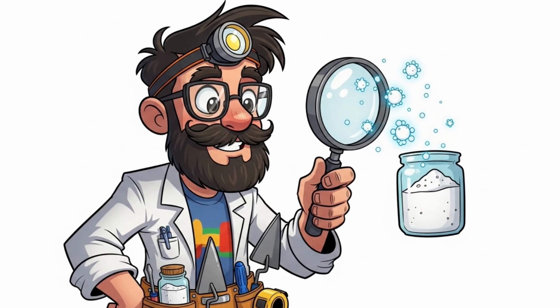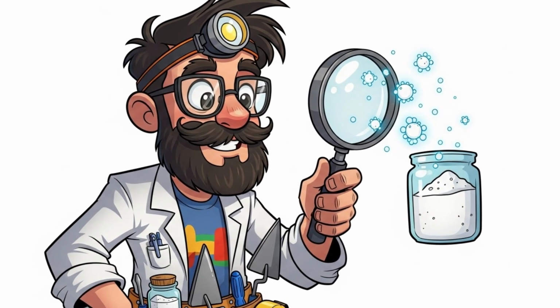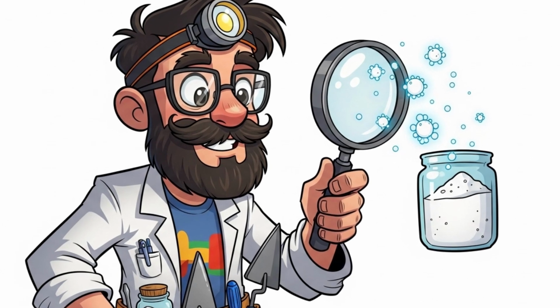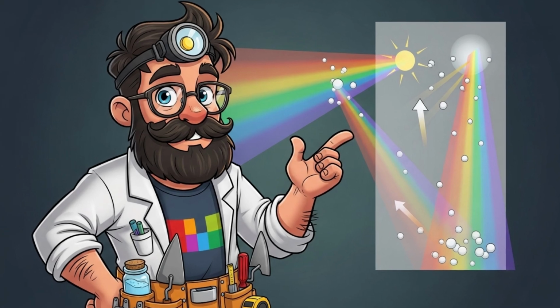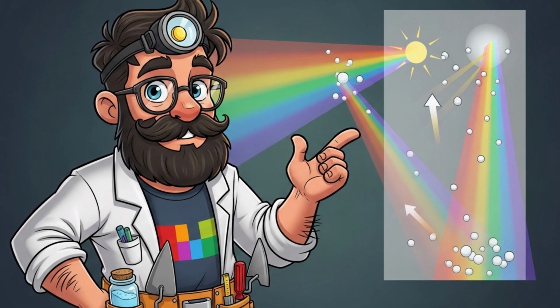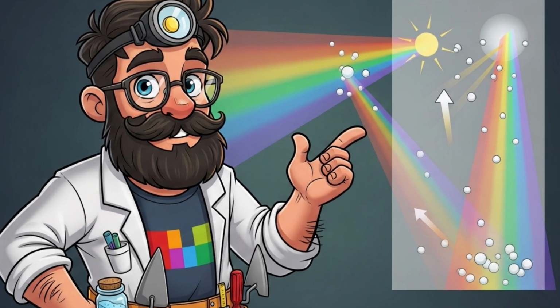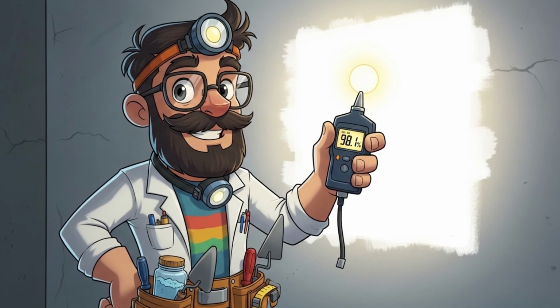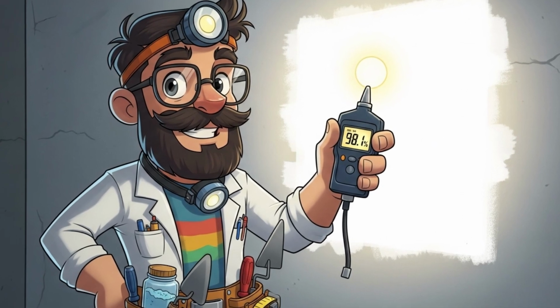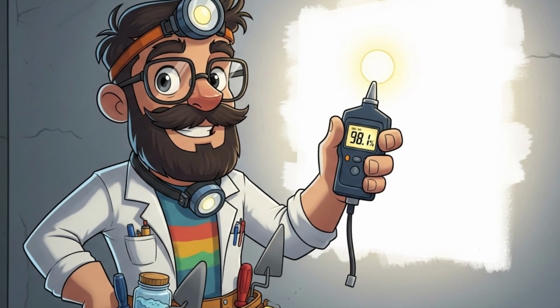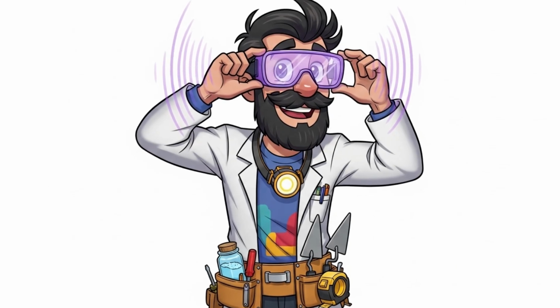Their paint uses barium sulfate nanoparticles at a 60% concentration in a carefully calibrated range of particle sizes. Each particle size scatters a different wavelength of sunlight. A wider range of sizes means a wider range of the solar spectrum is reflected. That yields 98.1% solar reflectance, which is extraordinary on its own. But the real breakthrough is what happens in the infrared.